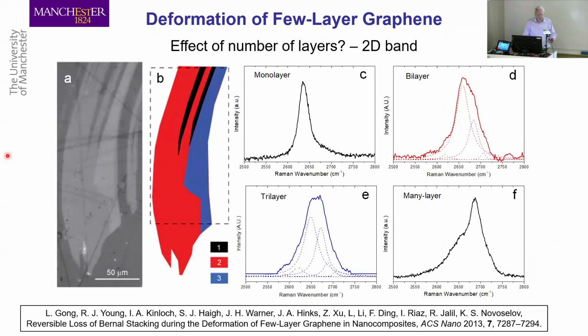So that was monolayer graphene. What happens if you have few layer graphene? Because we know once we get to graphite, the properties don't get anywhere near as good. And this is because the layers slide over each other fairly easily. So we looked at the deformation of this particular flake, and this is quite an interesting flake because it had black regions of monolayer, then red regions of bilayer, and then blue regions of trilayer. So we had monolayer, bilayer, and trilayer.